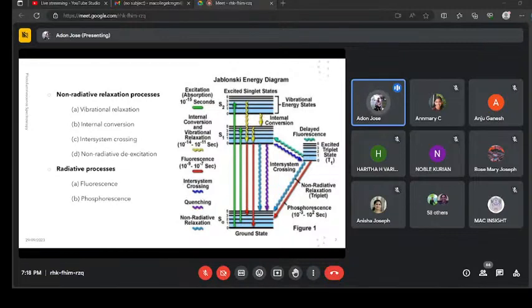And the fourth non-radiative relaxation process that we can define is non-radiative de-excitation. The non-radiative decay of excitation energy leads to the decay of the excited molecule to the ground electronic state, which is usually called de-excitation. The amount of energy released in this type of relaxation process is usually in the form of heat and is very small.